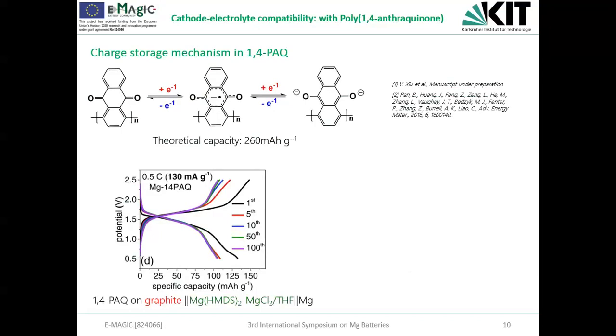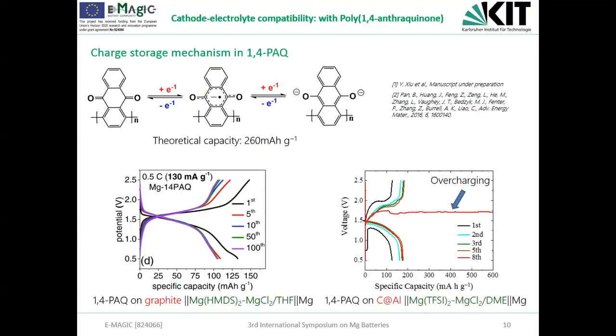On the other hand, we also noticed that they have used graphite as the current collector. The reason is quite simple: graphite is more anti-corrosive than normal aluminum foil. So we also did a comparison study using the chlorine-based electrolyte coupled with this polymer cathode, but we used carbon-coated aluminum as the current collector. As shown here, the cell could only be charged and discharged for a couple of cycles and then ended up with very long overcharging, which indicates some corrosion happening. So the corrosion can be mitigated by using a chlorine-free electrolyte system, but we also noticed that the low capacity might be from the cathode formulation.